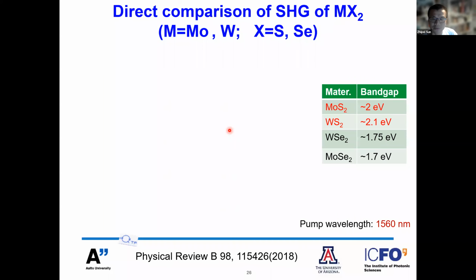At the beginning, we worked on this just for our own information, but then we found the results really surprising. Before we did the measurements, we did a very simple theoretical estimation. We know that the nonlinear optical response of materials is normally highly linked with the electrical band gap structure. So if we compare the electrical band gap structure of MoS2 and WS2, which are pretty similar, we can easily conclude that MoS2 and WS2 should have a pretty similar nonlinear response. A similar response should be expected from these two materials.